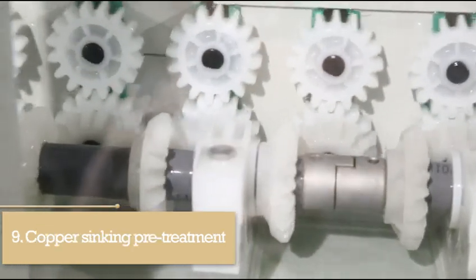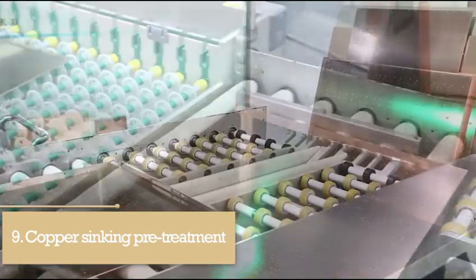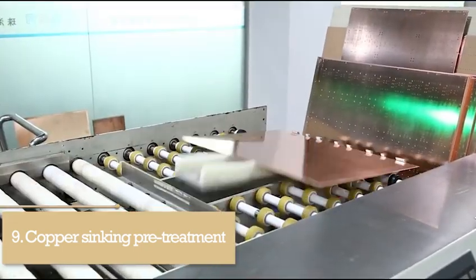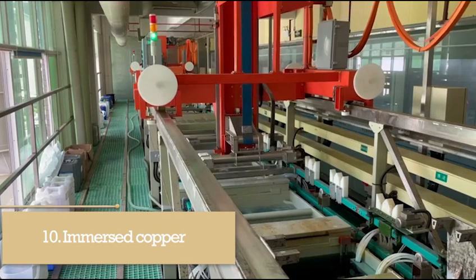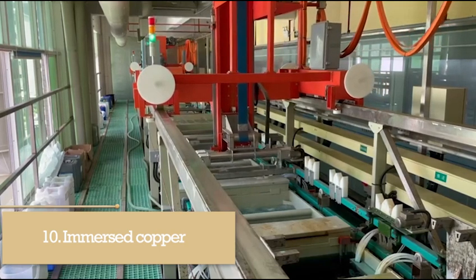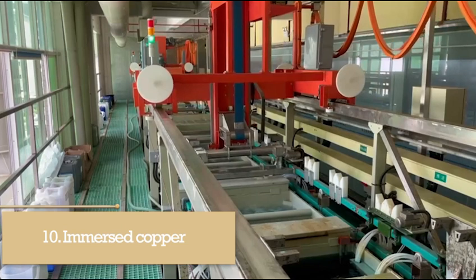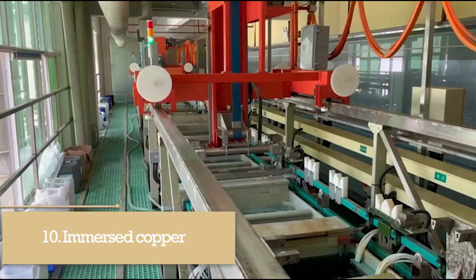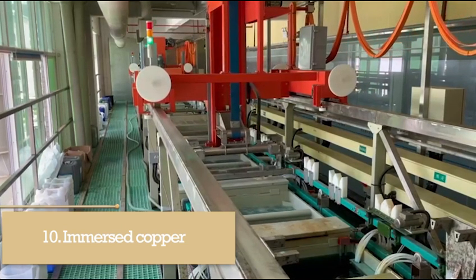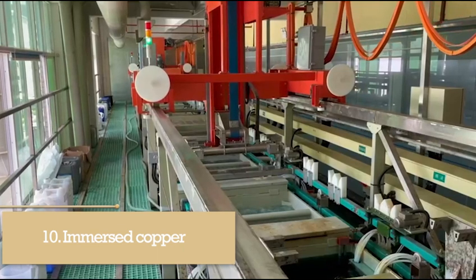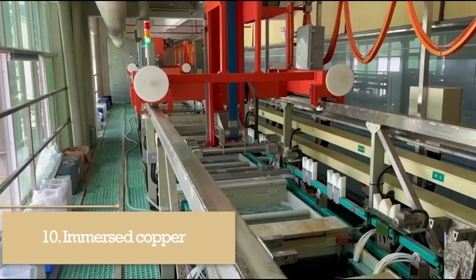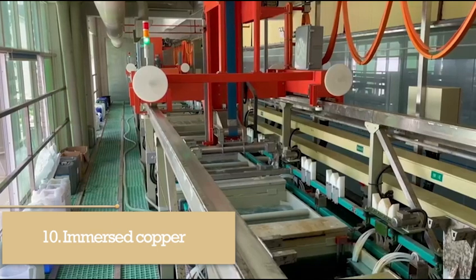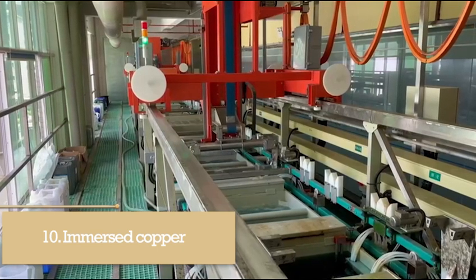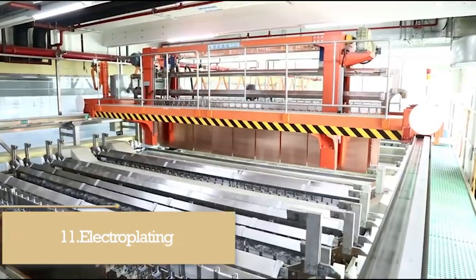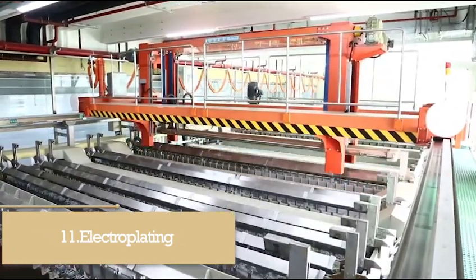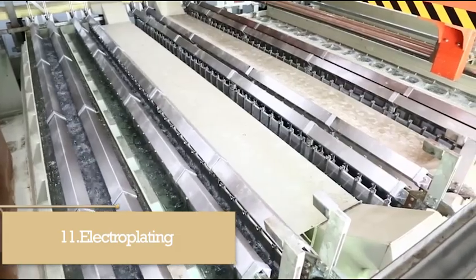9. Copper sinking pre-treatment. Chemical methods are used to clean and decontaminate the walls of drilled holes. 10. Immersed copper. It is also called chemical copper. After drilling, the PCB board undergoes an oxidation reduction reaction in the copper sinking cylinder to form a copper layer, thereby metallizing the holes, depositing copper on the surface of the original insulating base material, and achieving electrical communication between layers.